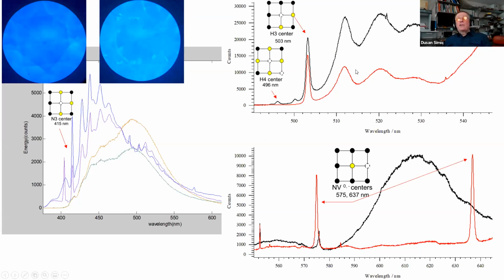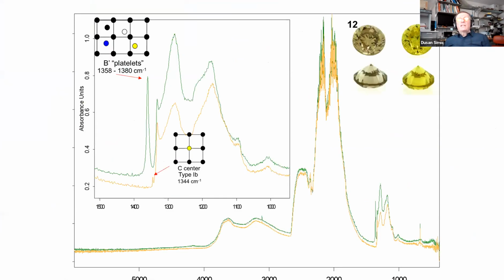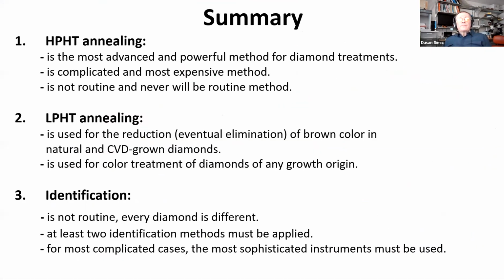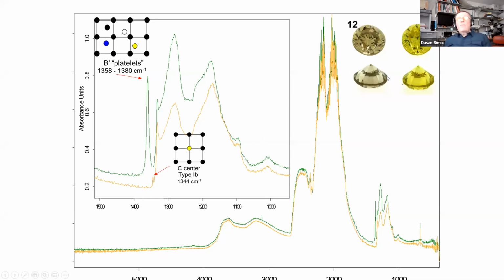And again, here it is interesting that the H4 center, also one of the less stable centers, is immediately annealed, and also the H3 center is decreased. Here are NV centers, as you prove that stone is HPHT annealed. And the last stone is interesting again because platelets, the interstitial atoms, are removed. They are bonded to the lattice. Single nitrogen is created. Here you see much more than in the previous, because simply the stones are different, you know.